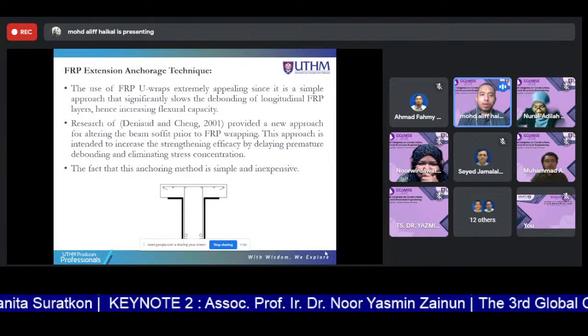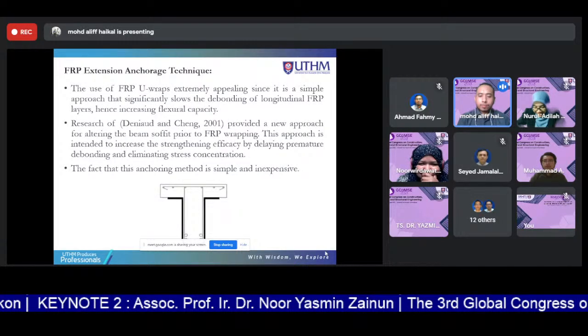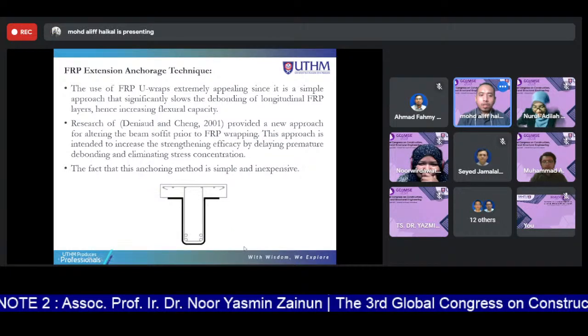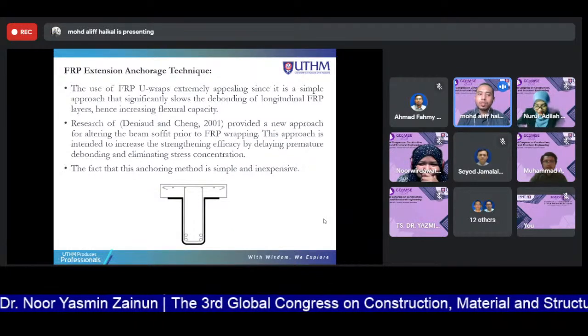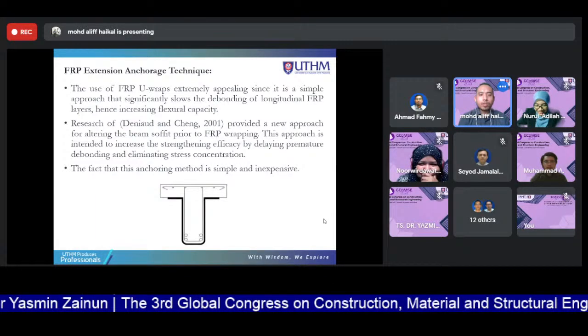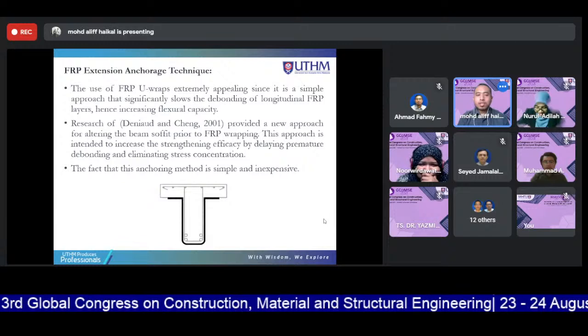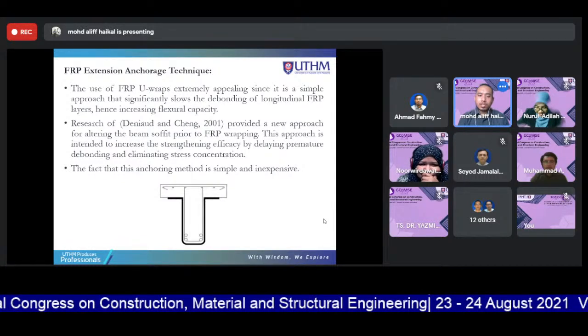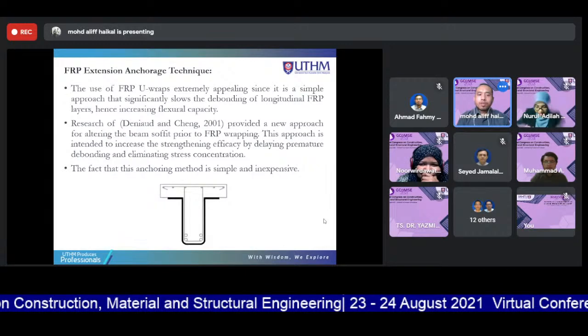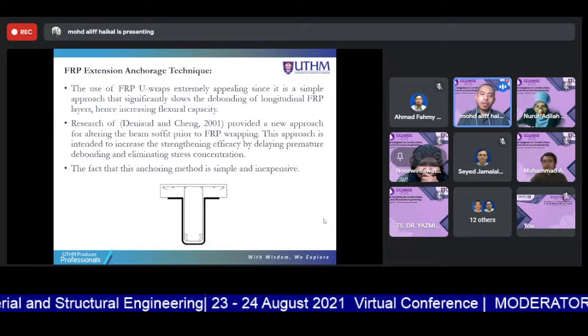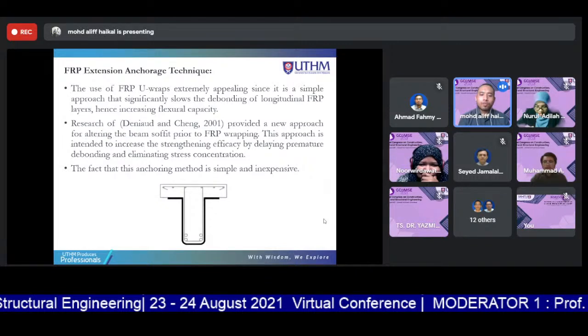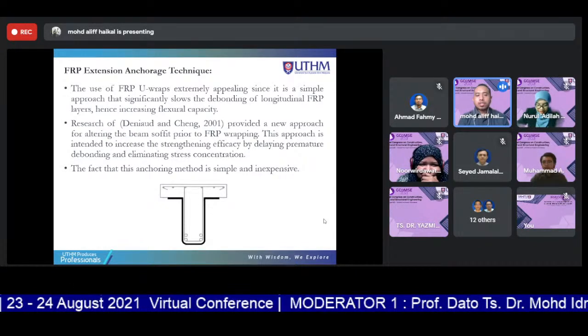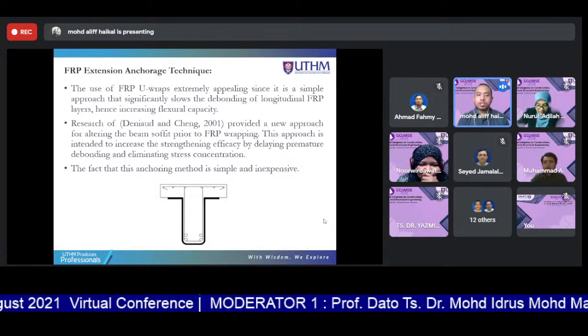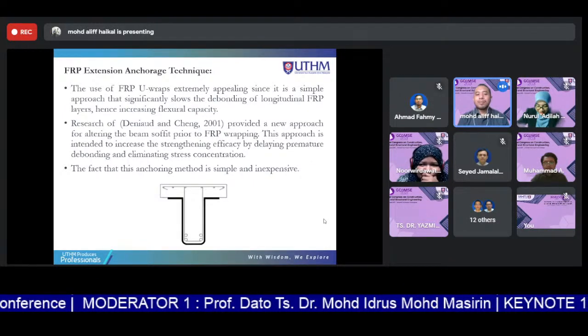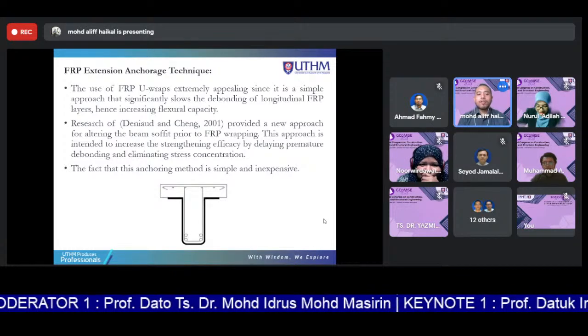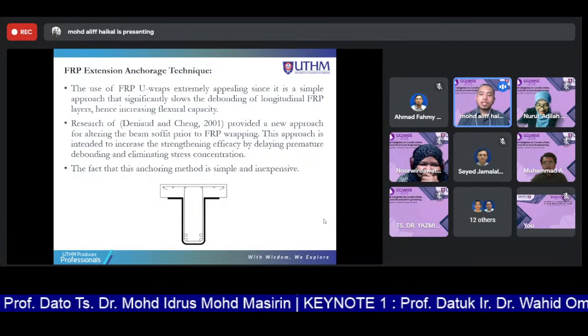And this one is the FRP extension anchorage technique. Externally applying FRP is a simple approach that significantly delays the debonding of the longitudinal FRP layer, hence increasing flexural capacity. Research by Deniaud and Cheng provides a new approach for altering the beam soffit prior to FRP wrapping. This approach is intended to increase the strengthening efficiency by delaying premature debonding and eliminating stress concentration. The fact is that this anchorage method is simple and inexpensive.